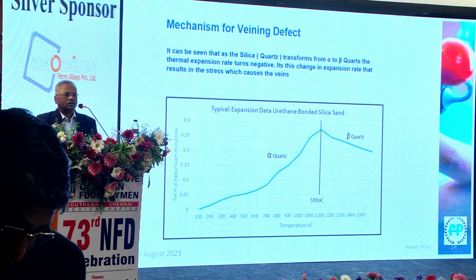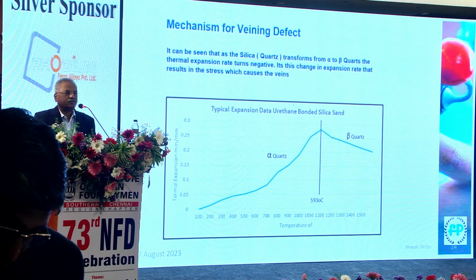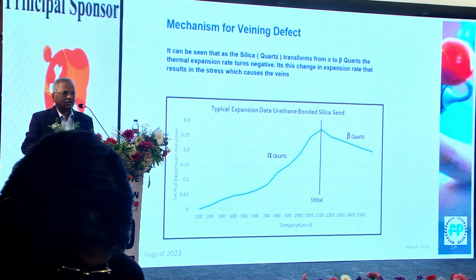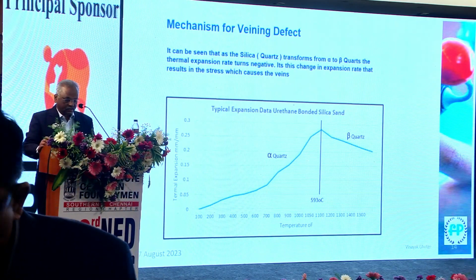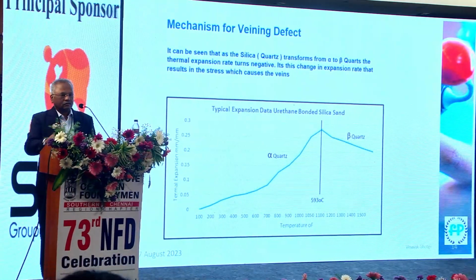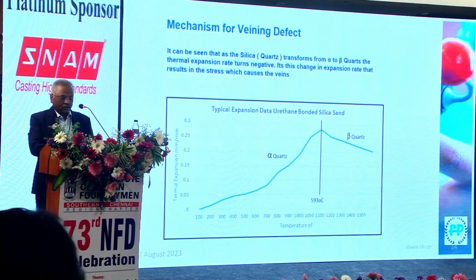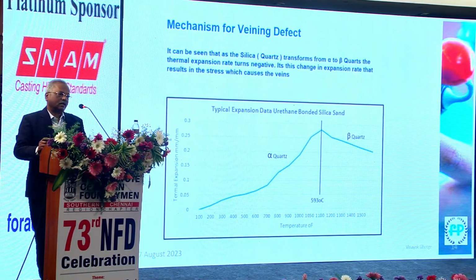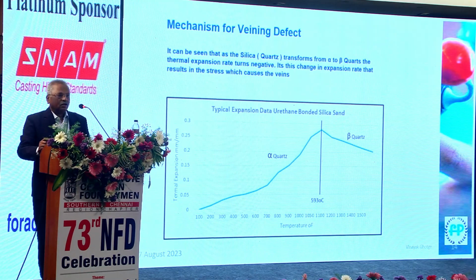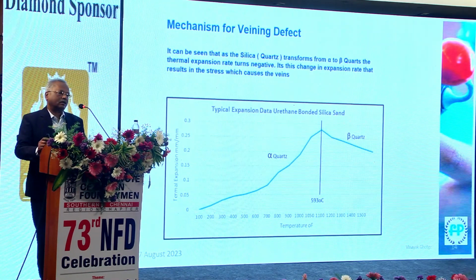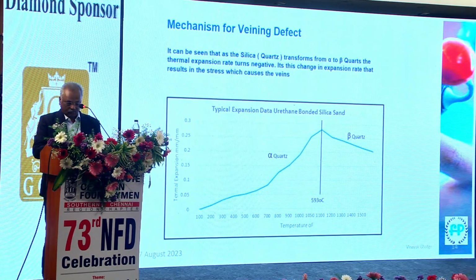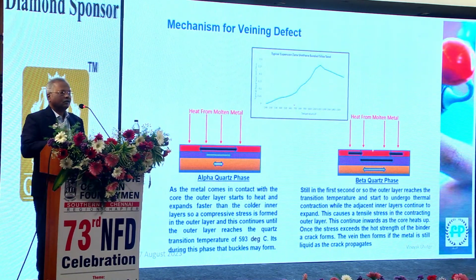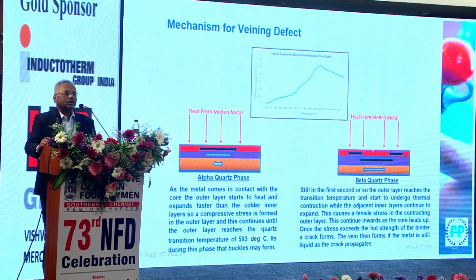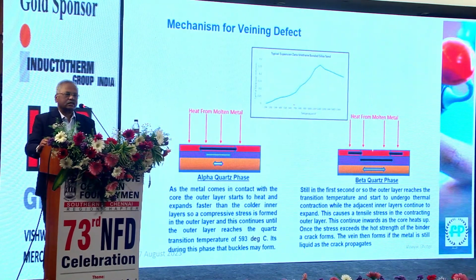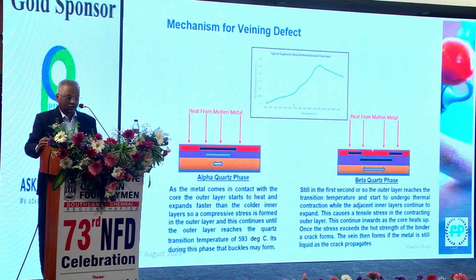As you know, silica sand has the ability to expand 2% by volume at a temperature of about 575 to 580 degrees centigrade, and the sand also converts from alpha phase to beta phase, and then there is a cooling also. Because of the heating and cooling cycle, stresses are developed in the core like this. And when the stresses are developed in the core, those stresses lead to cracking of the core. This is how the veining occurs in the casting.